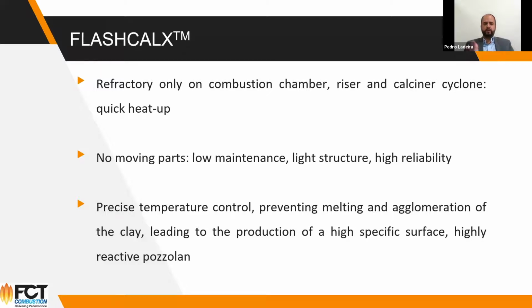The other thing is it's well known for the cement producers. There are no moving parts, so you can have low maintenance, a very light structure and a very reliable one. The other feature of the flash calciner is that you can achieve very precise control. So we can prevent melting, you can prevent agglomeration of the clay. You can lead to a very reactive and high surface pozzolan, which is very welcome. Again, remember when we've been talking about the temperature control and how we want to avoid crystallization of the structure. So when you have to have very precise control, you can achieve that with the flash calciner.